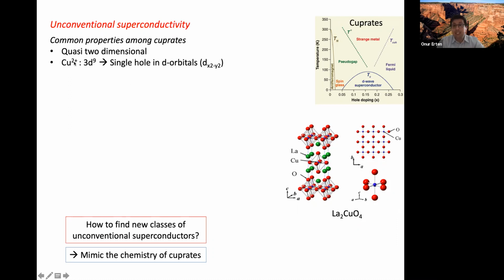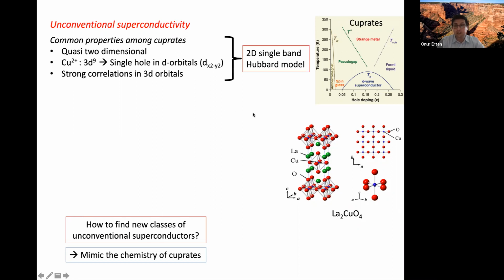And nominally, in the parent compound, when there's no doping, the copper is in a 2+ configuration. This is 3d9. This gives rise to a single hole in the 3d x squared minus y squared orbital. And well, the 3d orbitals are strongly correlated, so there's strong Coulomb interactions. And distilling all these three elements, Anderson, when these cuprates first came up, said that the minimal model to study cuprates is the two-dimensional single band Hubbard model.